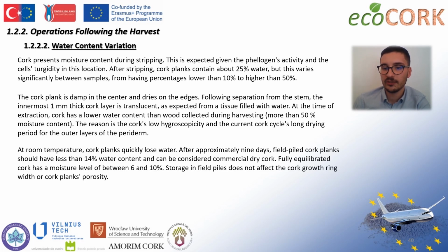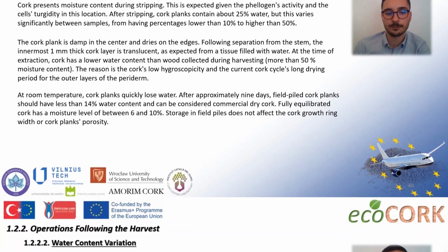After about 9 days of being stacked in the field, cork planks should have less than 14% water content and can be sold as dry cork. Cork that has reached equilibrium has a moisture level between 6 and 10%.